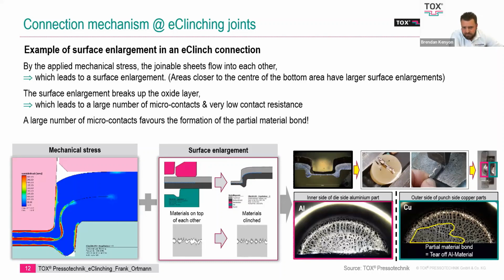And so what you see here is where we have made that joint and have done a cross section in order to evaluate that it is a very good contact, and then actually separated the two pieces of material so that way we can see. Here you have the actual aluminum, the bottom layer. And then what we're seeing is that contact point, those high contact points, we're actually getting an excellent bond between the two, that when trying to mechanically separate the two points, you can see that you're getting a mechanical joining of two surface layers of material, where you can actually see some deformation of the two materials trying to pull them apart.